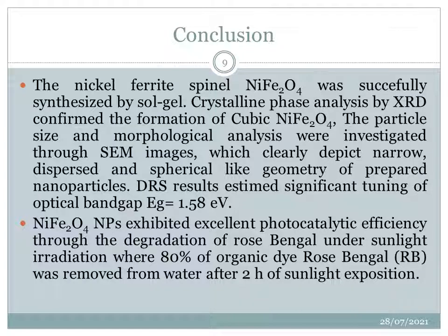Diffuse reflectance spectral results show the significant tuning of the optical band gap, which equals 1.58 electron volt. Nickel ferrite spinel nanoparticles exhibited excellent photocatalytic efficiency in the degradation of rose Bengal under sunlight radiation, where about 80% of the organic dye rose Bengal was removed from water after 2 hours of sunlight exposure.